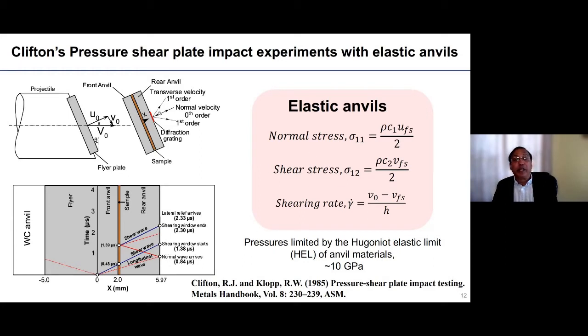As I mentioned, you make interferometric measurements of the normal velocity and also the transverse velocity. In Professor Clifton's lab, this is done using a normal displacement interferometer and a transverse displacement interferometer, which was developed by Kim and Clifton. Because one can use the characteristic analysis, in this case simple elastic characteristic analysis, the longitudinal impedance times the normal particle velocity gives you the normal stress, and the shear stress similarly can be calculated using the shear impedance and the shear particle velocity. The interesting relationship exploited by this technique, which is why it is a direct measurement technique, is that the strain rate is simply given by the impact transverse velocity, which is the imposed boundary condition, minus the transverse free surface velocity, divided by the thickness of the sample.